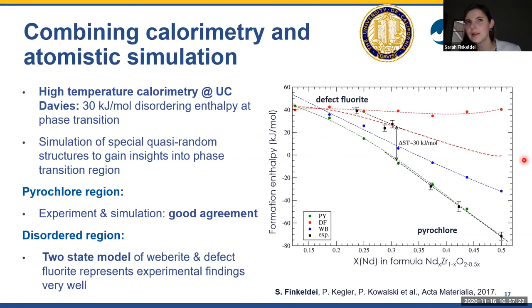So maybe I'm misunderstanding how this works, but you were talking about switching between different forms of the defect fluorite and the pyrochlore. When we look at these plots, the defect fluorite is the red line at the top, is that right? Yeah, this is the defect fluorite, the modeled one. The black dots are the experimentally derived values from the high temperature solution calorimetry measurements. When we derived those formation enthalpies with quasi-random structures, we obtained these values for a defect fluorite and those for a weberite.